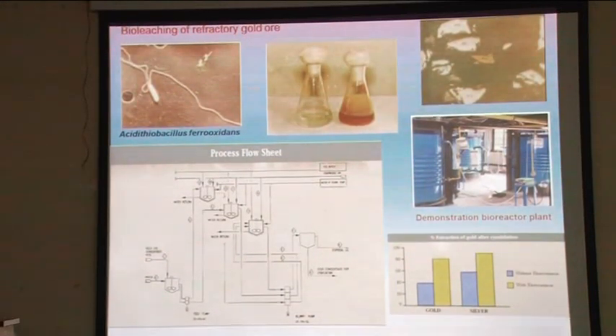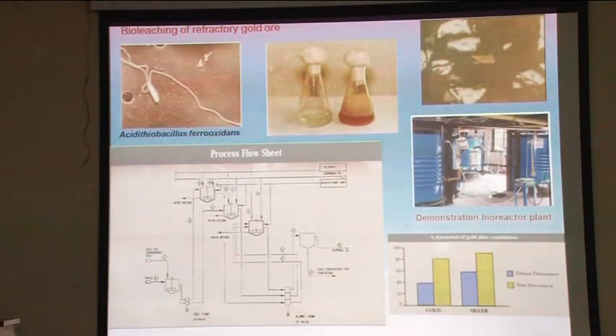Here you have the process flow sheet that has been developed for the bioreactors. These are the three-stage bioreactors that have been erected there. Basically, the slurry of the gold ore is taken in presence of sulfuric acid, there is a retention time of about 48 hours where the sulfide is oxidized to the sulfate. The context here is the pyrite and arsenopyrite.